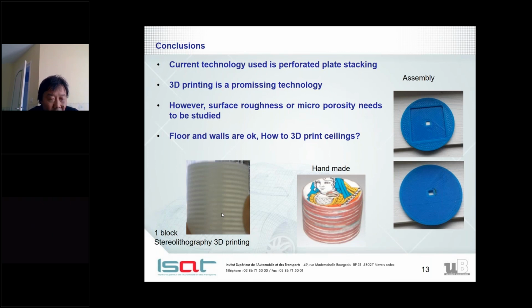Here is an example of a 3D printed sample, not made by us, but by a company. And the technology was all right here because I think they use 3D stereolithography printing. And here it is clear when you look at the sample that you don't have these problems with microporosity. So in this case, the match between theoretical and experimental results was all right.